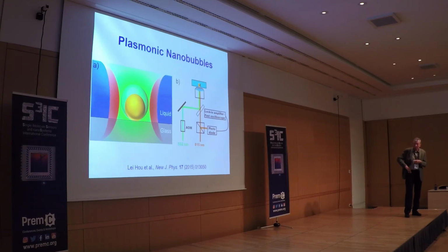But of course, it's very sensitive to look at a bubble, because a bubble is a huge perturbation in refractive index. If you just heat a little bit, you modify the index of refraction by maybe 1 or 2 digits. If you change from liquid to steam, to vapor, the change of index of refraction is from 1.3 or 1.4 to 1. So it's a huge effect on the plasmon and on the scattering.